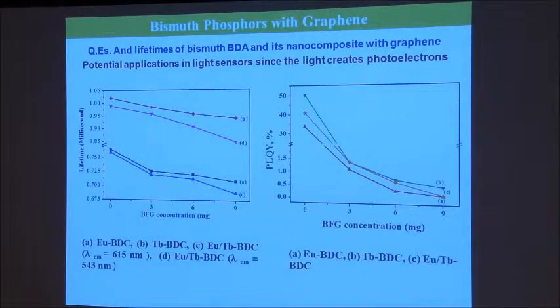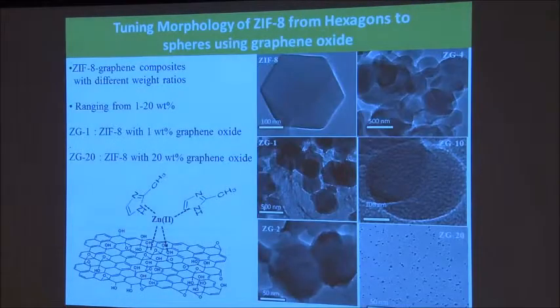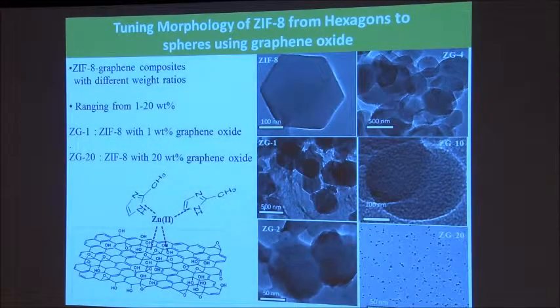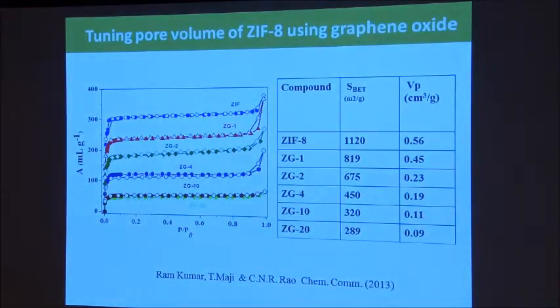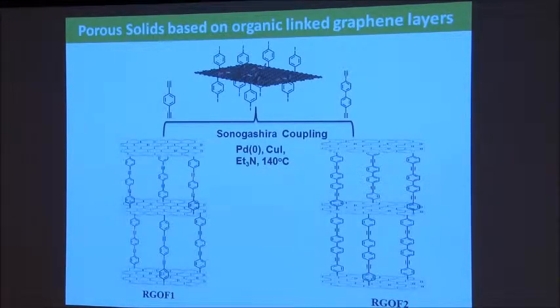So this is one thing we have, not yet published, something we have done. One thing we have published just recently is a composite with a very well-known metal organic framework, ZIF-8. Everybody knows it, everybody works on that. It is the imidazolate metal organic framework. This is graphene - we grow that imidazolate on the graphene and make a composite out of that. You can see it has wonderful surface area properties, varying with the graphene content. But what is interesting is it also has very interesting carbon dioxide absorption.